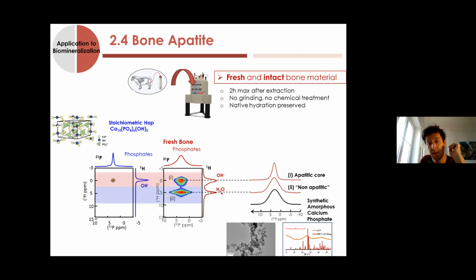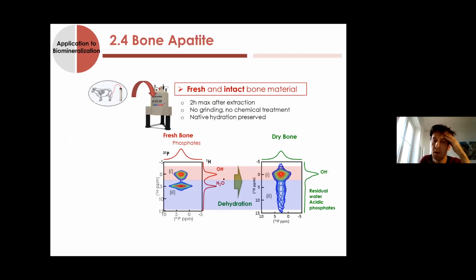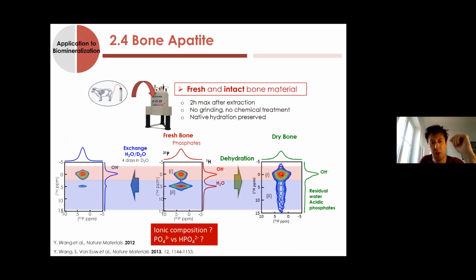Why at the surface? Because that peak is correlating with water molecules. You can assign it due to the chemical shift, but also because if you dehydrate the sample, you see a strong modification of that peak and no particular modification of the other one. You can also make an exchange between proton and deuterium, and then you see that peak disappear. So it really corresponds to the surface of the particles in a water environment.